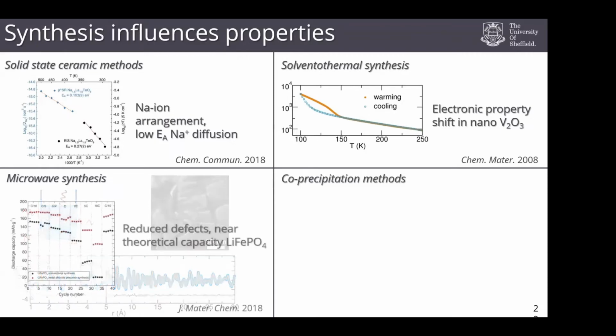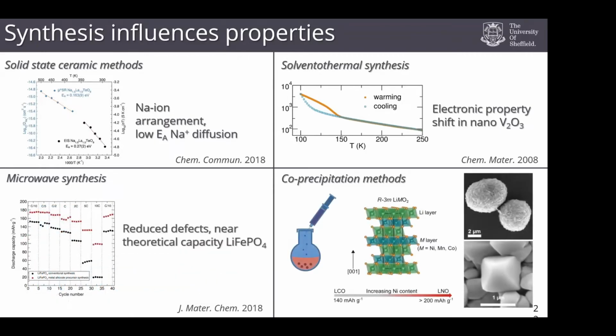I also use co-precipitation methods. So this is where if I want to make something quite complex, like this lithium nickel manganese cobalt oxide or NMC material, I can add together all of the constituent parts. I can really tightly control the pH, the stirring rate, and the temperature, lots and lots of parameters that you can start to refine here, so that you can actually develop spherical assemblies of individual particles that aggregate into these large spheres. That's really important because these are the kinds of arrangements that give you high energy density in lithium-ion batteries. So being able to control that is really important.